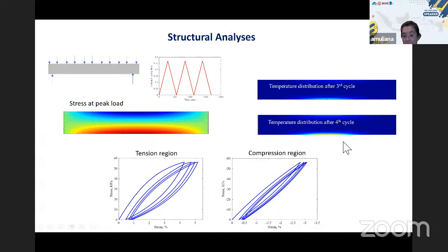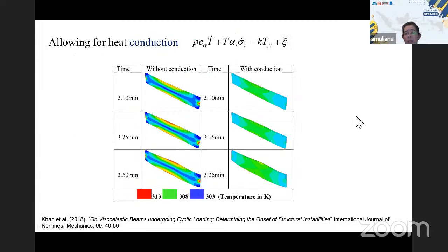So that would increase the body temperature, right? So the consequence of this is that the materials are very sensitive to temperature, so this would also lead to what we call later on instability. So this is just to show the simulation, when we allow the heat conduction, right? So this part is due to the dissipation as you continue the cyclic loading. So we'll see temperature build up, right? As the temperature continues to increase, the polymer gets softened. So we'll see through the simulation buckling, or a loss of stability in this component.